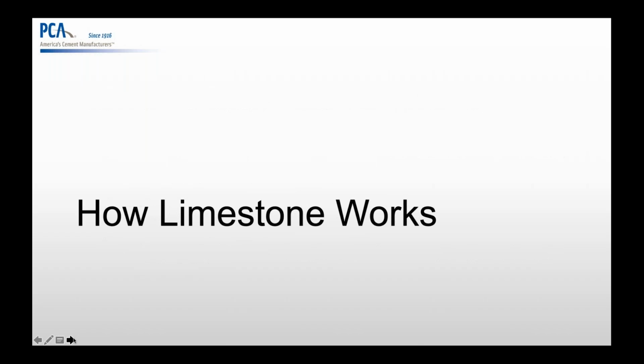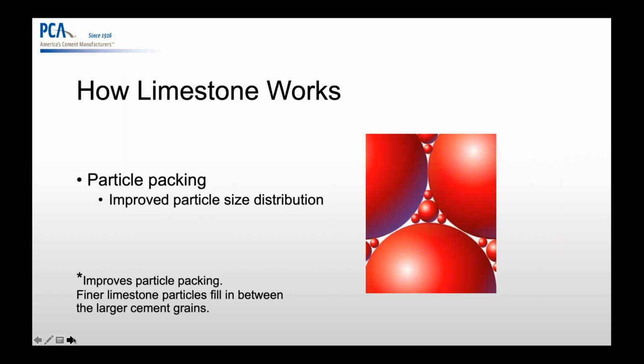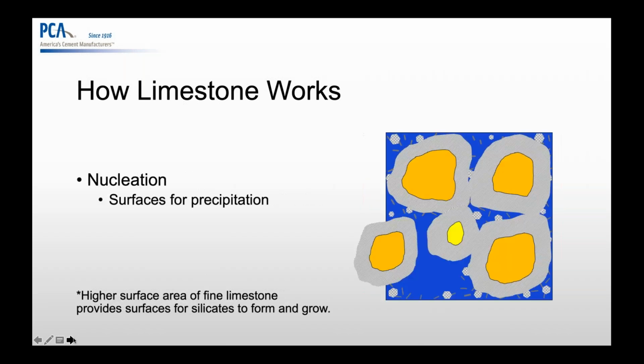I mean, understanding that limestone is an inert material, there are different mechanisms. One in particular is the particle packing. So we understand that the clinker and the limestone are ground at the same time. The limestone being a softer material than clinker, you'll have more fine particles. Those fine particles will find their way into the voids in between the clinker particles, meaning that you will have a more dense material and denser concrete at the end of the day. So particle packing would be one of the big mechanisms here that we bank on with the PLCs.